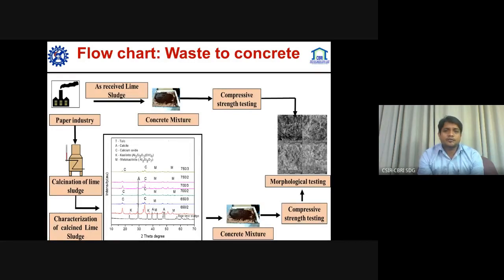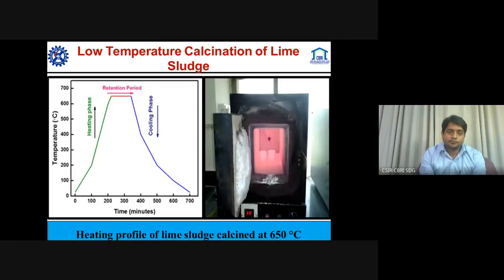Again, the flow chart for the low temperature treatment of lime sludge and then utilization in concrete. So the calcination of lime sludge was performed, and mineralogical analysis was performed. Then it was put in concrete, and other properties were tested, and the same thing was also done with as-received lime sludge. As-received lime sludge was used in concrete, and the compressive strength and other properties were tested.